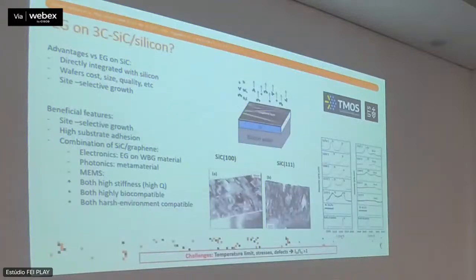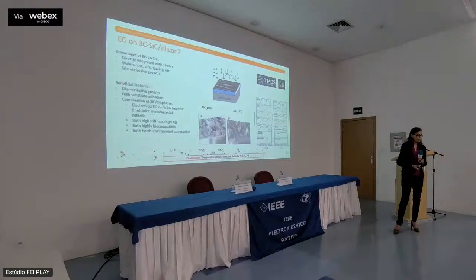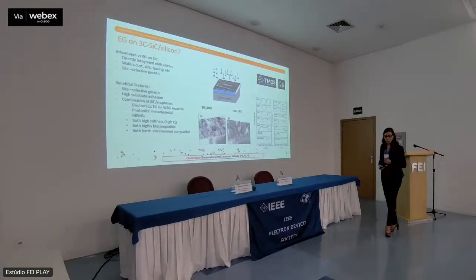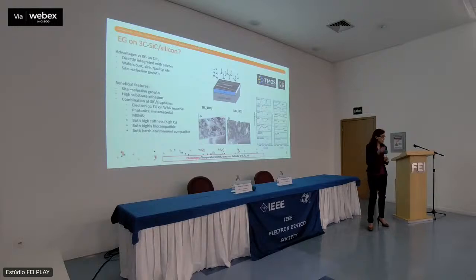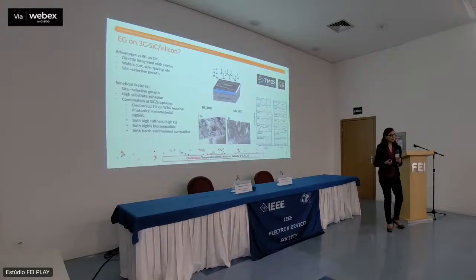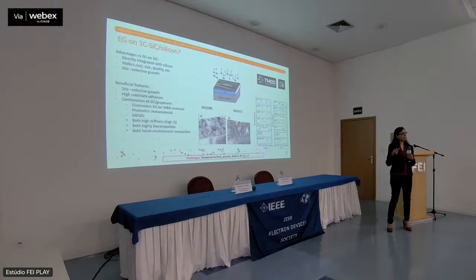But we said that we were interested in doing this on silicon, and there are quite a lot of reasons for it. As you know, most of the infrastructure nowadays in semiconductors is based on silicon. It would be really good to be able to combine silicon technologies with graphene technologies. So we were really interested in whether we can do the same by using silicon substrates instead. The obvious initial idea would be that silicon carbide can be grown onto silicon. So if we have that, why don't we try to do the same, bring everything to high temperature and play with the same system?